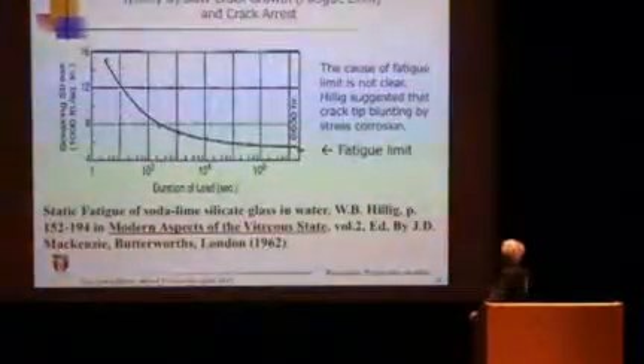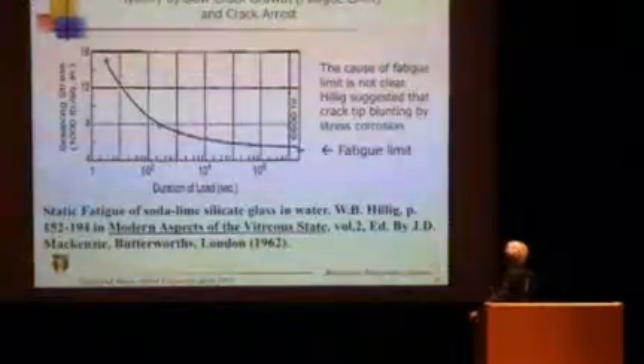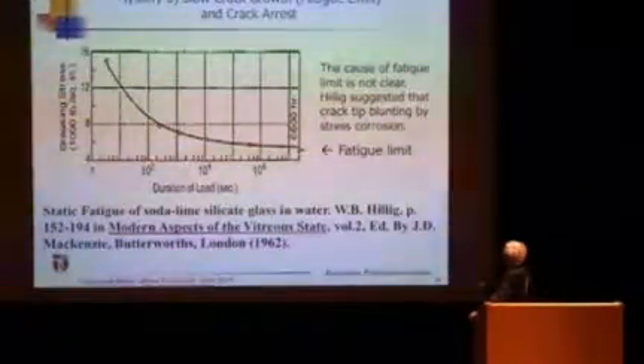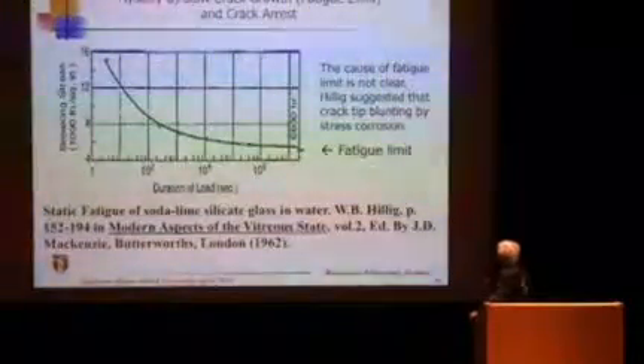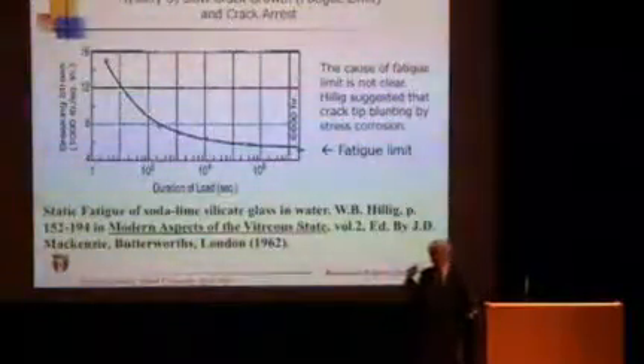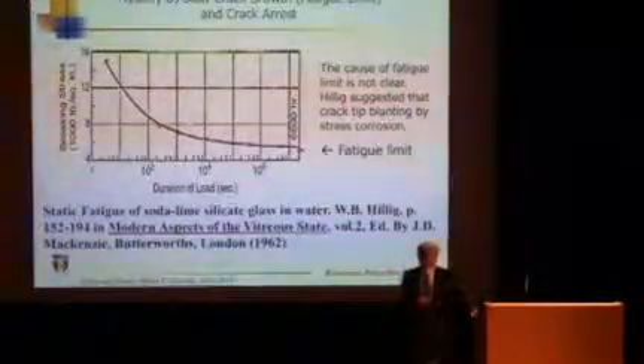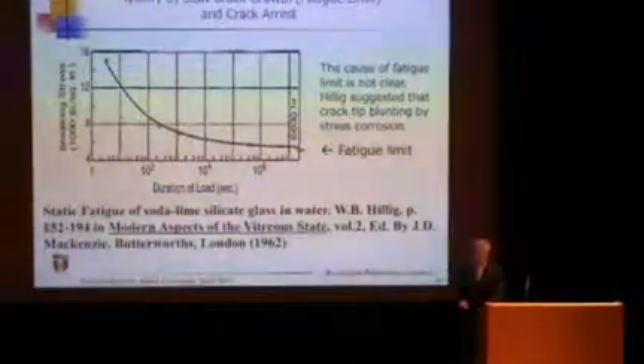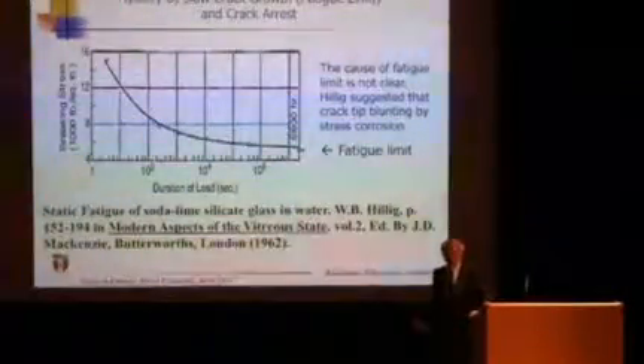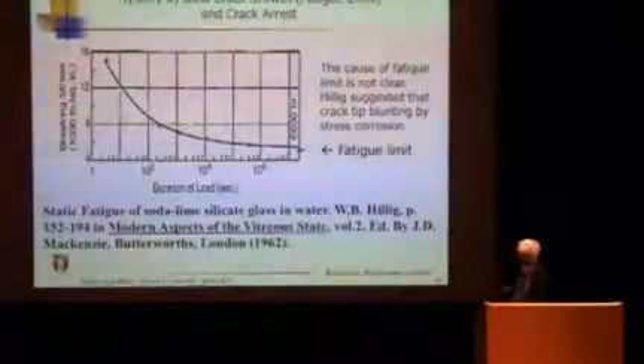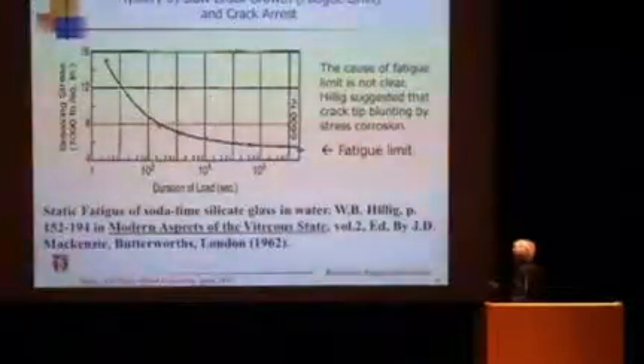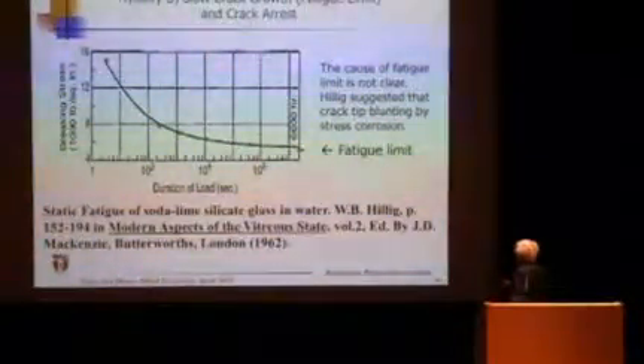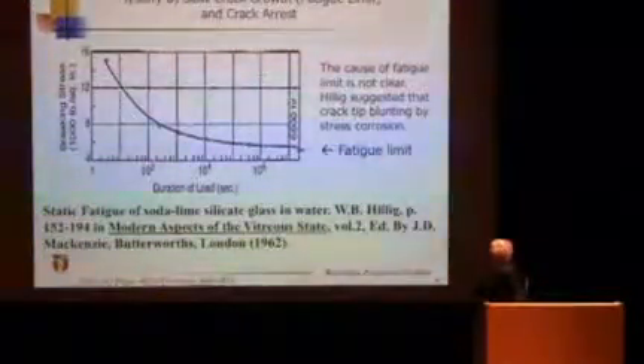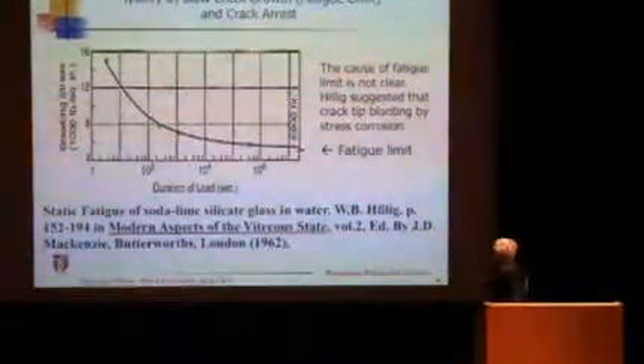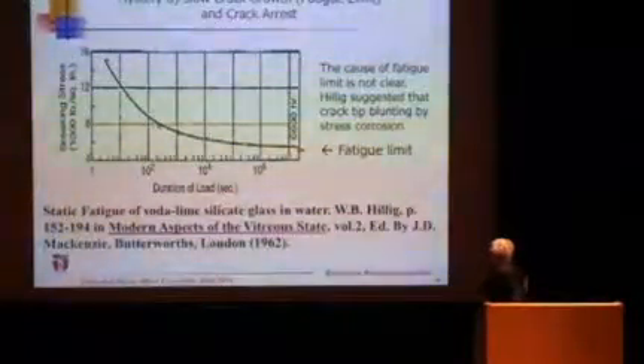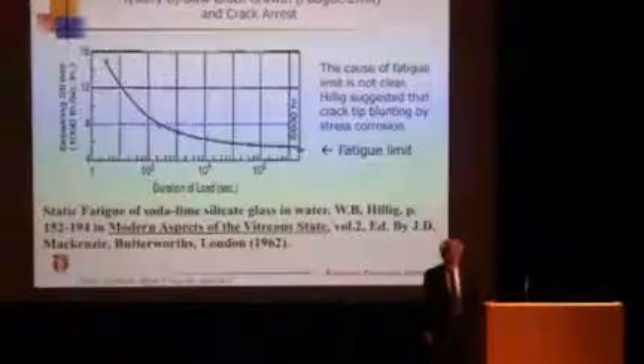This is soda lime glass in water, tested, initially stronger at short time, weaker later, and this is roughly 1 year. So this type of experiment is very valuable, but it's not appropriate as a PhD thesis. One gets very old by the time you finish this research. So this has been available, and even though the strength is coming down, it starts to saturate, and that's a very good thing, that if you apply this load, it will never break. As long as you stay below this load, that product can be used for years to come.